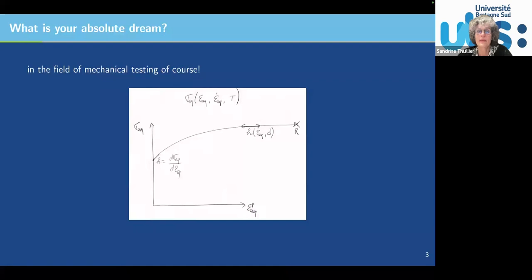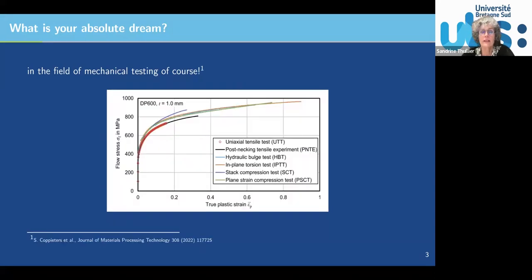And this dream, in order to reach it, you need several mechanical tests. And I think we are not that far. And here is, from the literature, an example of this, the flow stress as a function of the true plastic strain. And it's not one curve, but we are coming closer and closer. But in order to have this, you have all these tests to characterize the mechanical behavior. So mechanical testing is a key to reach my dream.